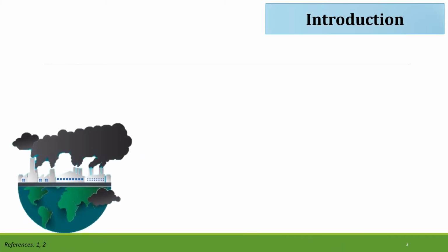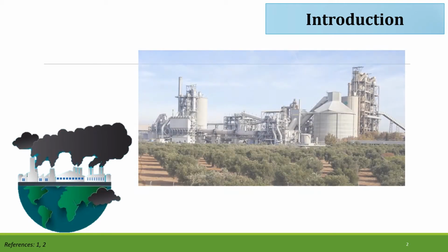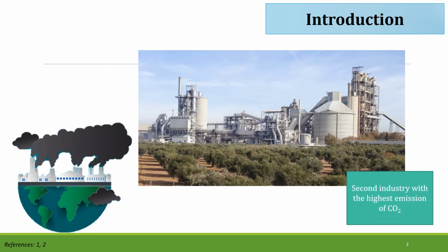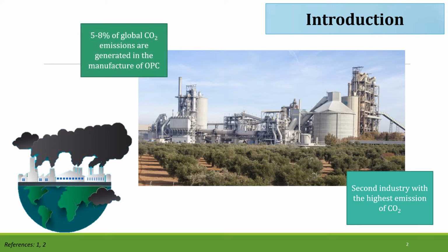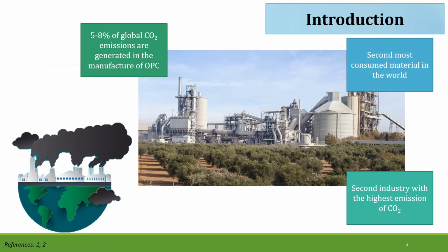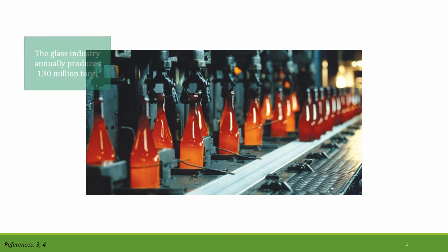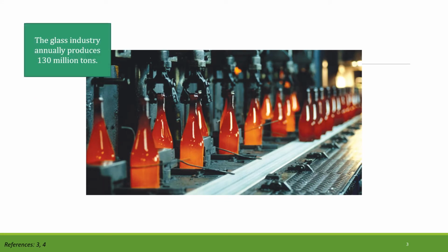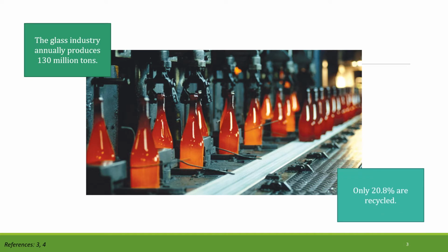Currently, reducing carbon dioxide emissions and solid waste are some of the global challenges. In this context, the cement industry is the second industry with the highest emission of carbon dioxide into the atmosphere, responsible for 5 to 8% of the emissions of this greenhouse gas, and is the second most consumed material in the world, only behind water. For its part, the glass industry annually produces around 130 million tons, of which only 27 million tons are recycled. So about 80% of the glass goes to landfills.